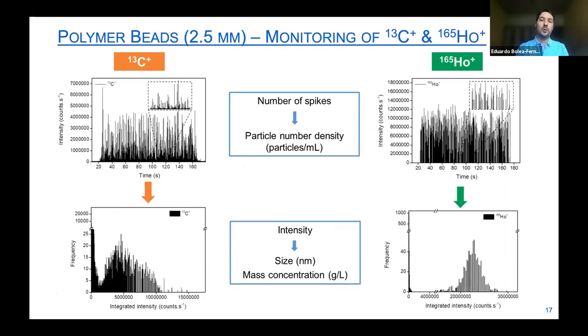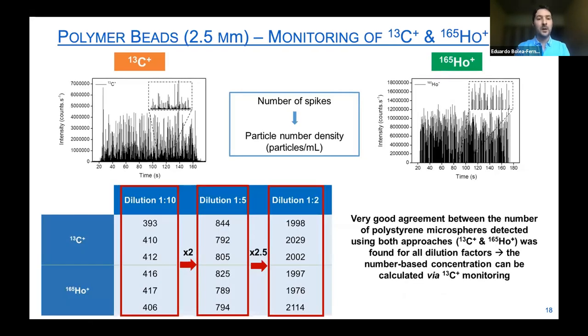So basically, we wanted to answer all our questions. We wanted to see if it would be possible to obtain the particle number density, so the number based concentration, which means the number of particles, in this case the number of microplastics per unit of volume, in this case particles per milliliter, by knowing the number of events or the number of spikes detected. We also wanted to know if it would be possible to get some additional information from the intensity of those individual spikes. So first, we focus on the number of spikes and the calculation of the particle number density or the number based concentration. And for this, we compare the results obtained when monitoring 13 carbon. We selected 13 carbon because 12 carbon, which is the most abundant carbon isotope, was considered a bit risky for the detector of our ICP-MS instrument. So we decided to go for the lowest abundant carbon isotope.